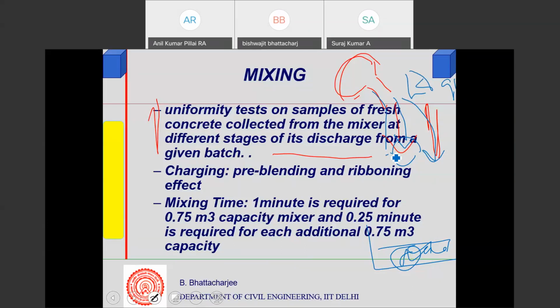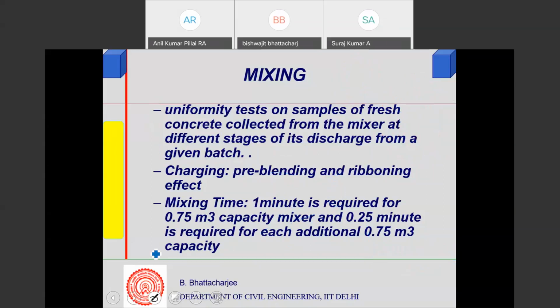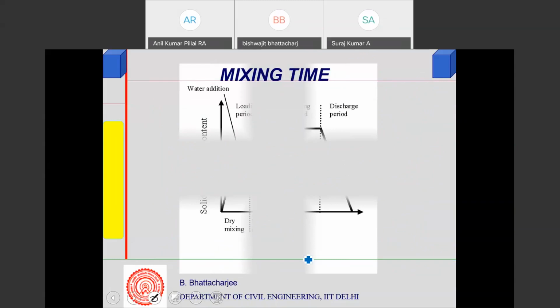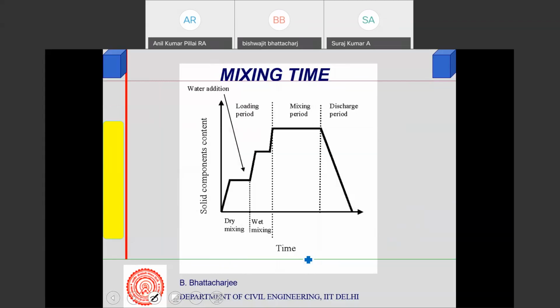Itself introduces a variation. Then I was talking about charging and blending. Charging, pre-blending, ribboning effect, etc. These are all issues actually. Now, certain guidelines give you 1 minute is required for 0.75 m3 capacity mixer, and 0.25 minute is required for each additional 0.75 m3 capacity. Okay, guidelines. But my point is, this is the best way: dry mixing for the solid components content in the mixer. Then some water is added here. Wet mixing and final water added here. Then mixing period, then discharge period. That's a good kind of a practice.